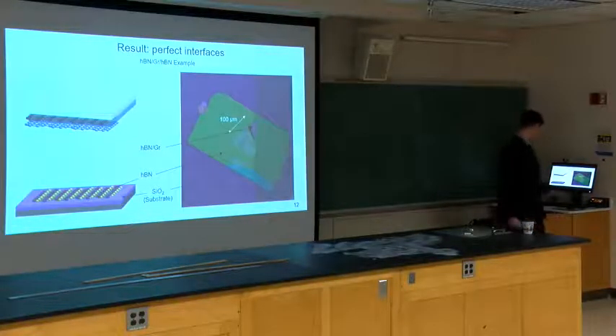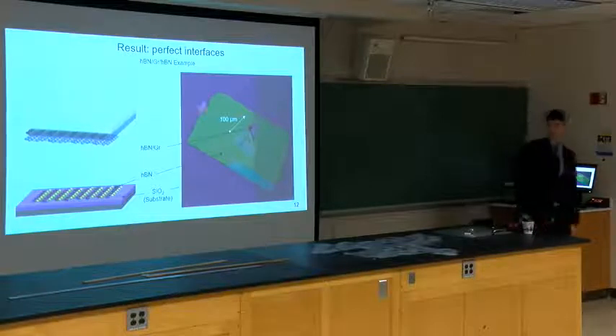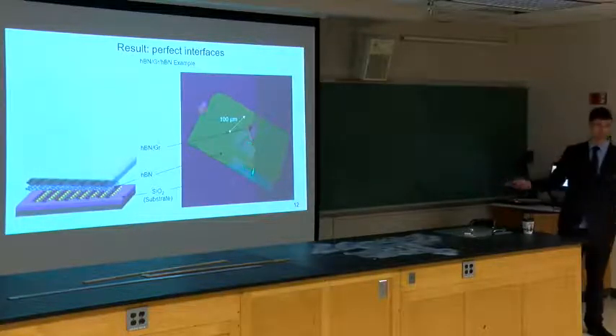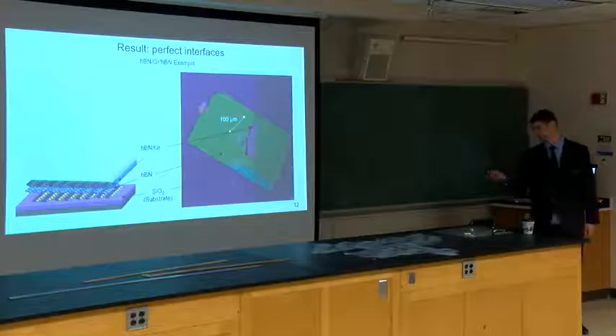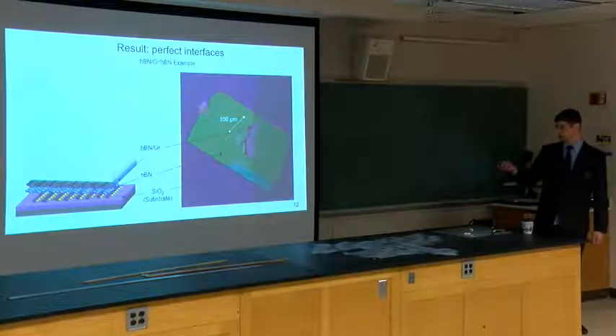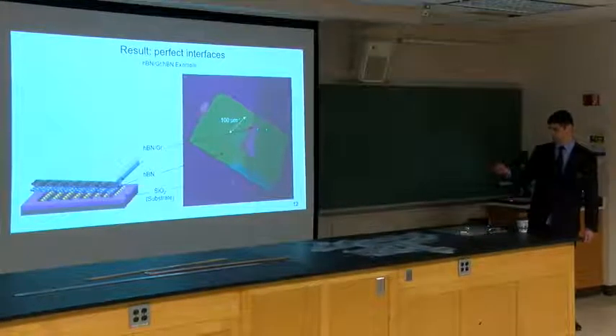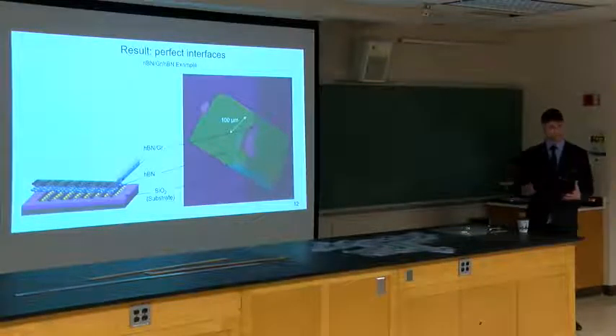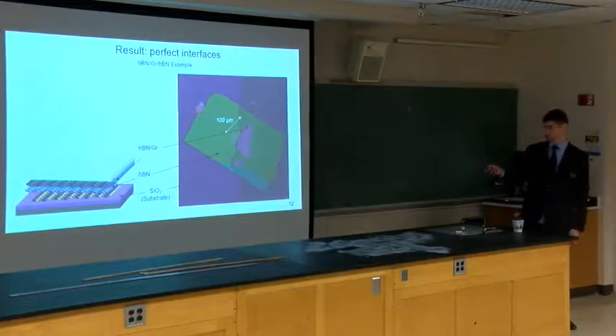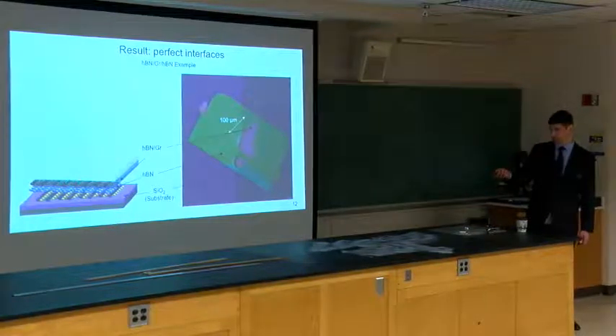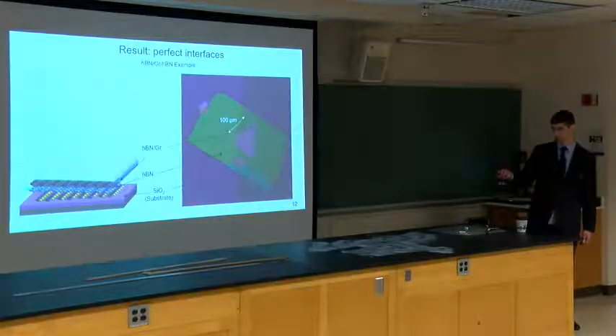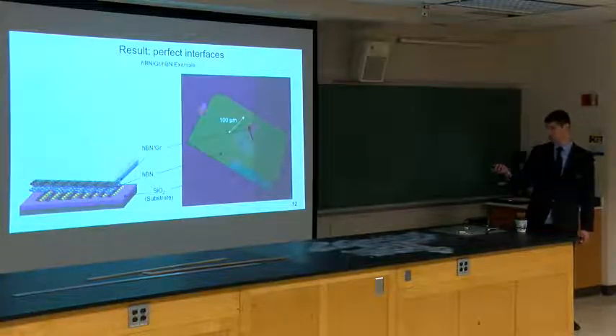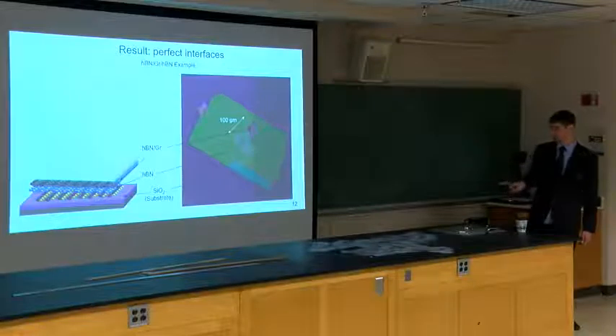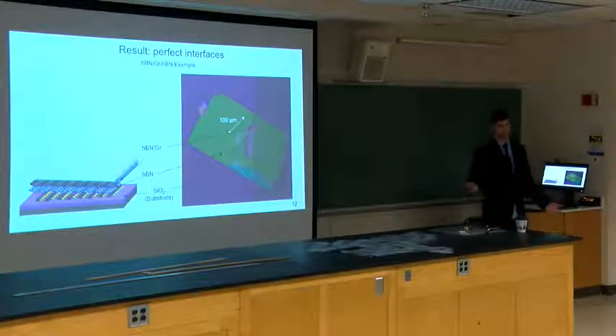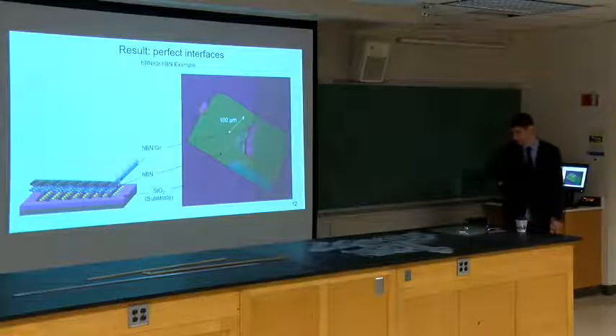So this is one actual transfer that I did a few years ago, and the scale here is about 100 microns. So we're still dealing with small flakes. We don't have wafer scale things. This transfer is, as the diagram showed, just putting down the hBN graphene stack onto a bottom hBN, which is this large piece, and this is the hBN graphene. This transfer actually took about 2 hours to do, and this is the result.